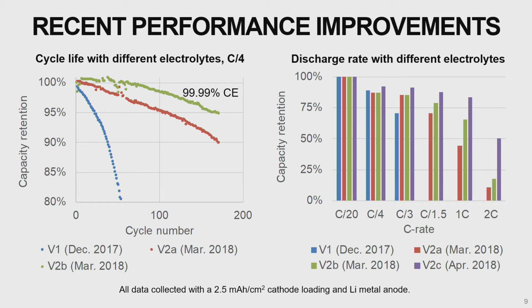So this is C rate, which is basically how fast you're discharging the battery, where C over 20 is a 20-hour discharge, 1C is a 1-hour continuous discharge to full depth of discharge. And you can see for our most recent electrolyte now, this V2C from April, we're able to do a 1C discharge still with more than 80% of the theoretical capacity. So on the power side, especially given the high specific energy of this chemistry, we already have enough continuous power and also pulse power probably for a variety of electric flight applications with this new chemistry.